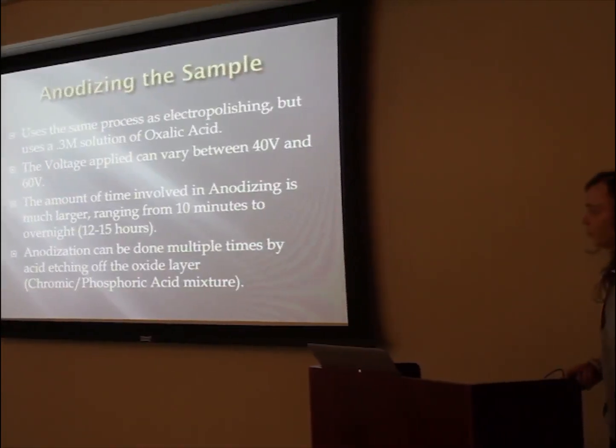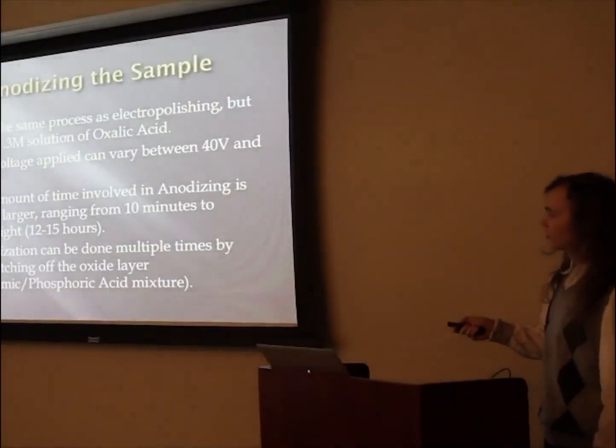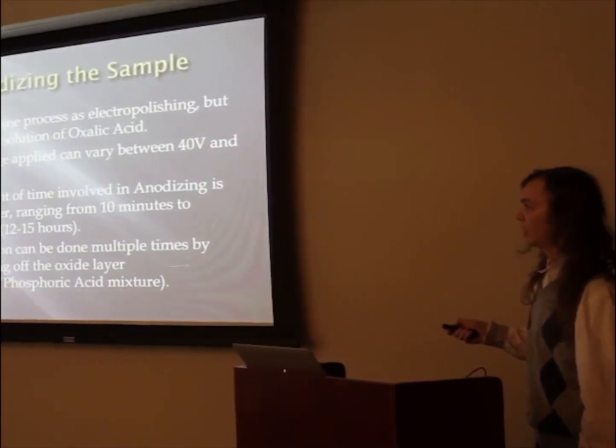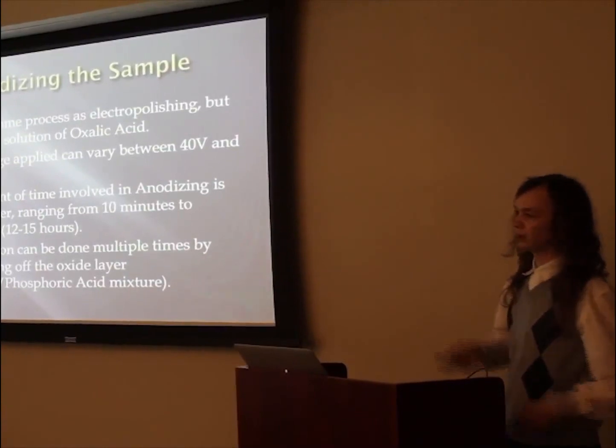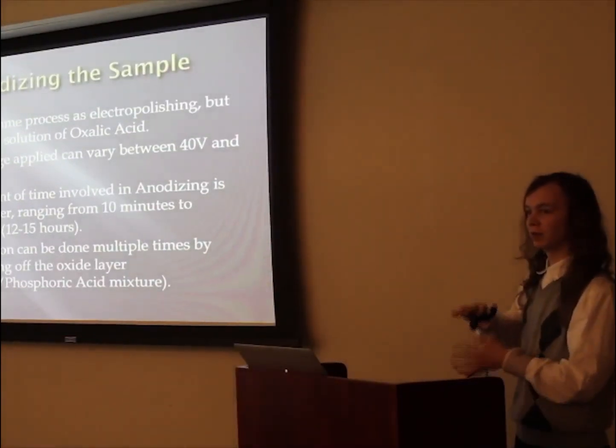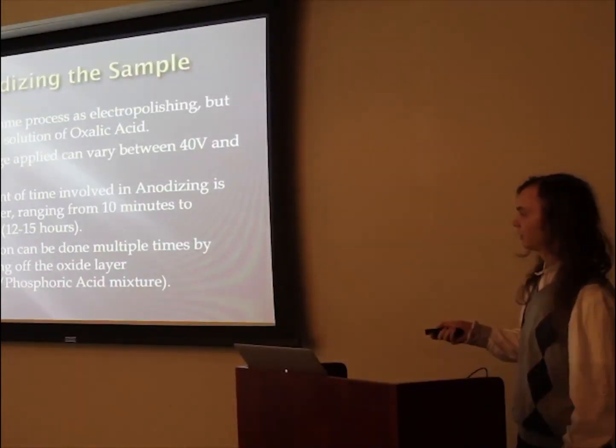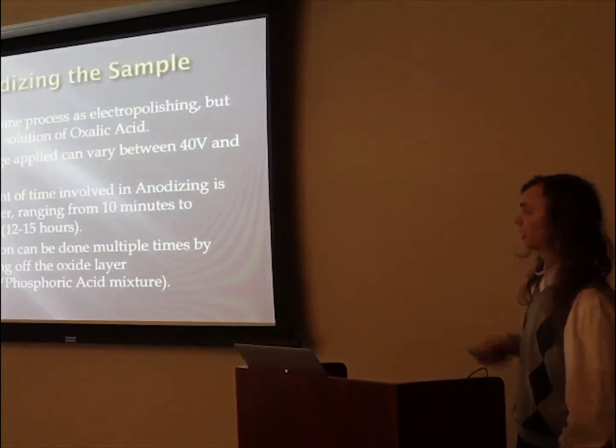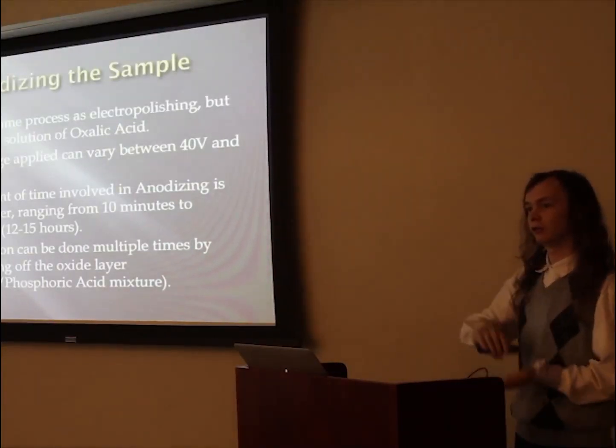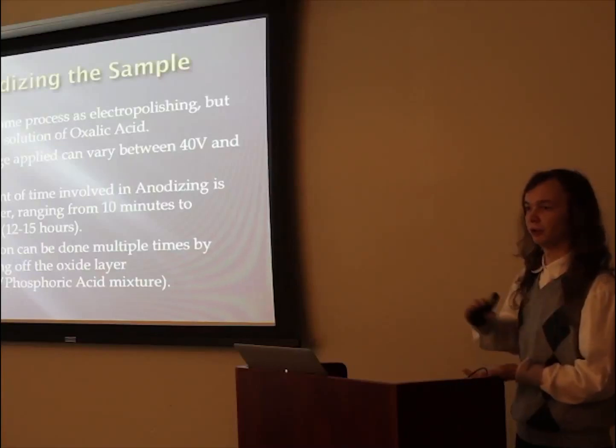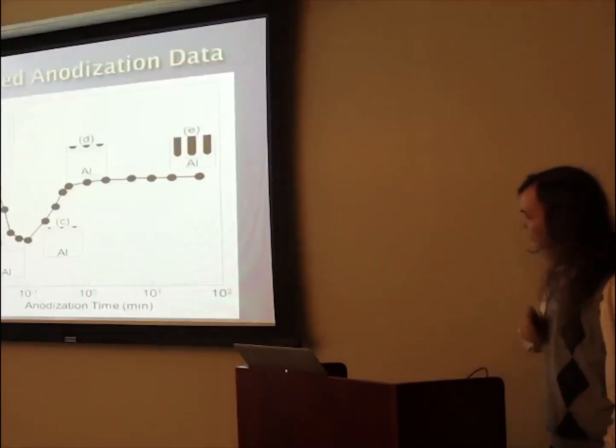So the range of time for anodizing it can vary greatly, and we use the parameter of time to actually optimize this system. And along with that, there's another parameter we can talk about, and that's anodizing multiple times. So if you anodize it the first time, make an oxide layer at the top, making some of these pores, you can etch that oxide layer off from the top with a chromic and phosphoric acid mixture, and that allows you to anodize it again later, possibly doing anodization in multiple steps.